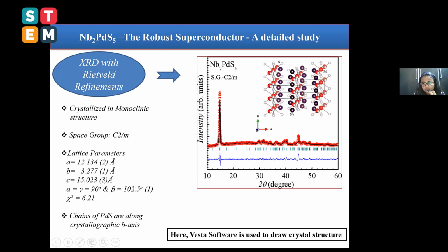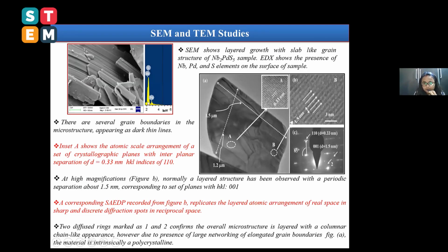This is the structure drawn using VESTA software, using the parameters obtained from Rietveld refinement. What we found is that there is a chain of PdS along the b direction. And this is the SEM and TEM study of the Nb2PdS5 sample. SEM shows a layered-like growth structure, while TEM shows several grain boundaries in the microstructure appearing as dark thin lines. Inside, it shows the atomic arrangement of a set of crystallographic planes with interplanar spacing 0.33 nanometer.